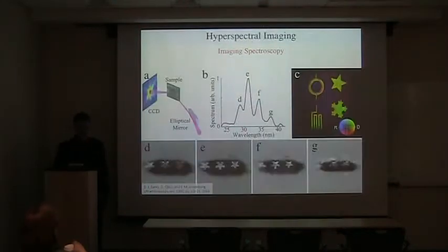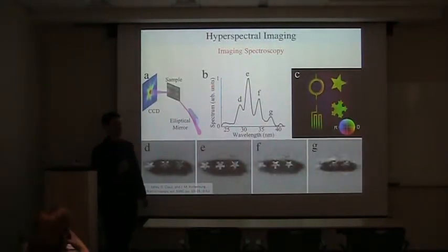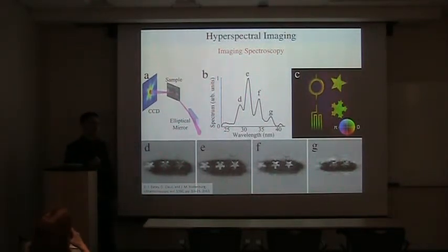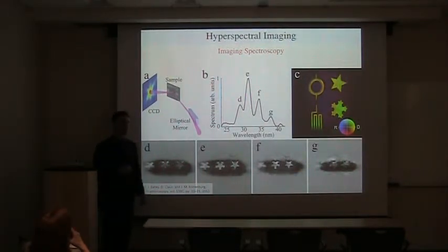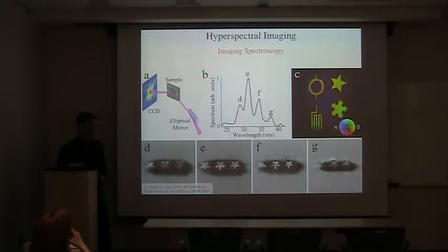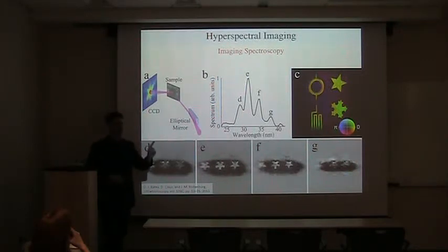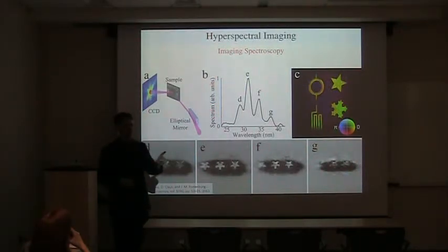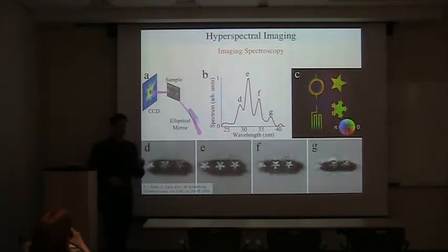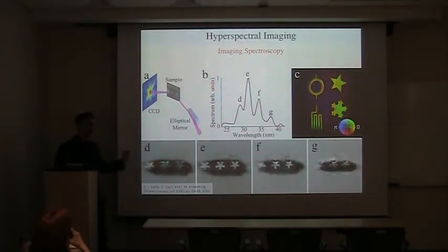One other thing that it can do, which is quite amazing, this was very surprising actually, is that there's enough redundant information that we can actually now deal with sources of decoherence in our beam. One source of decoherence is spectral decoherence. If you have multiple wavelengths that are shining on the sample simultaneously, it turns out that ptychography can rip apart that diffraction pattern that's composed of an intensity average over the wavelengths and get a diffraction pattern for each of the colors and make a reconstruction of the object for each color also.